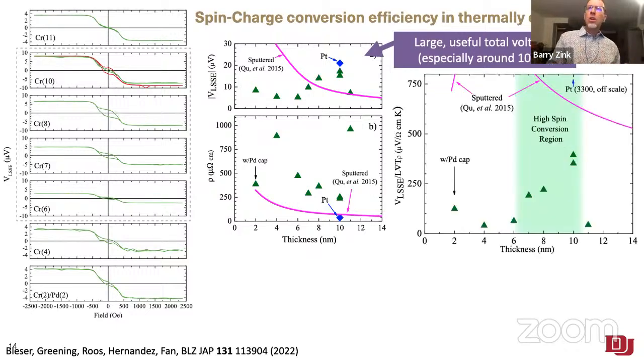Right? So if you go ahead and convert all this to the spin charge conversion efficiency, that's scaling out all the things that are simple, like the geometry, the resistivity, and of course the size of the thermal gradient that you've applied. Then you get this plot here on the right, and you can see that in the case of the evaporated stuff, we see a very different dependence on thickness than was seen in sputtered chromium and other more boring materials. And so we have this weird high spin conversion region where the spin conversion goes up and then shuts back off again.